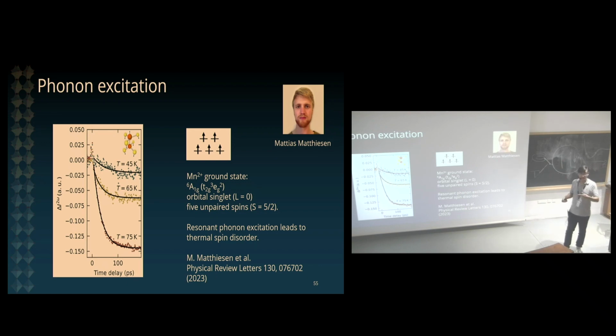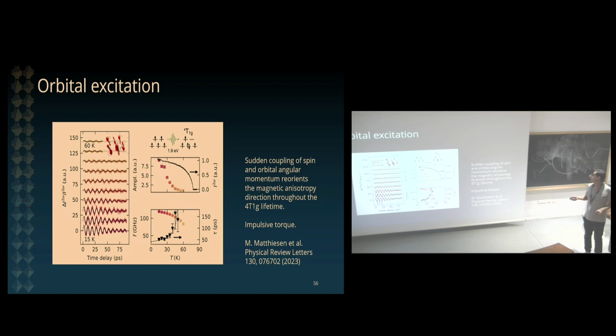Okay. This is in contrast with the dysprosium orthoferrite case, where the dysprosium atom is bringing about strong spin-orbit coupling effects. In particular, this antisymmetric superexchange or Dzyaloshinskii-Moriya interaction, which is giving us this spin canting and this strong sensitivity of the lattice and magnetism, strong coupling of lattice and magnetism. Okay, so that's one of the key points, if you want, of the seminar. You need spin-orbit. However, in manganese thiophosphate, you can play a different game.